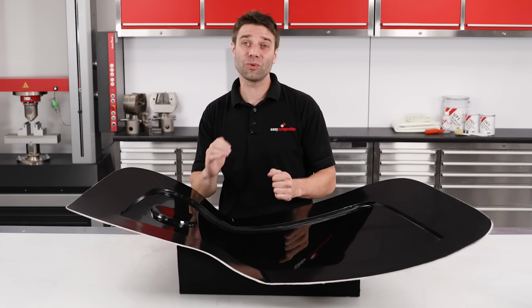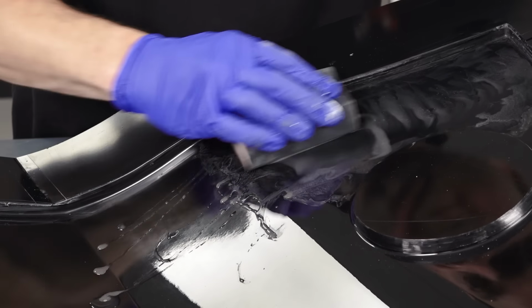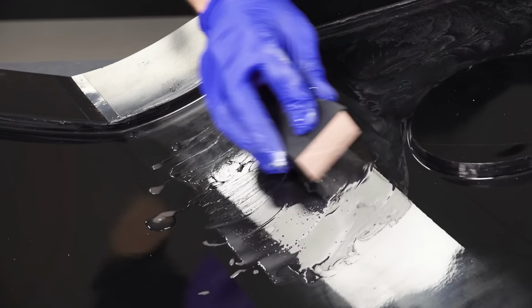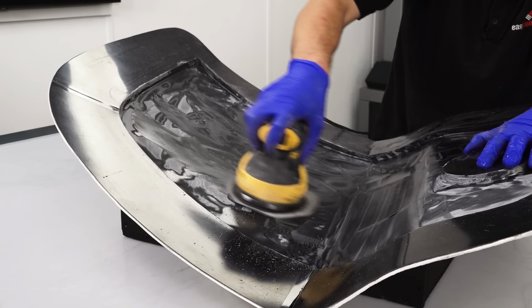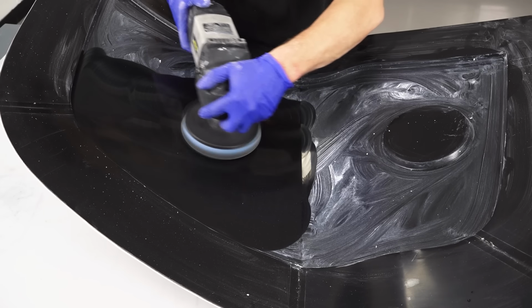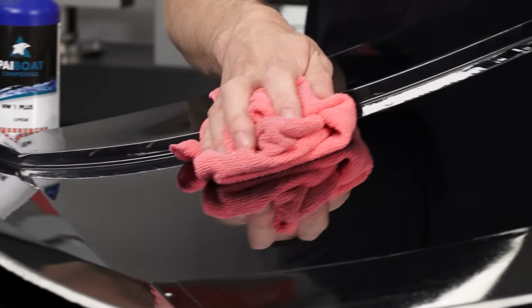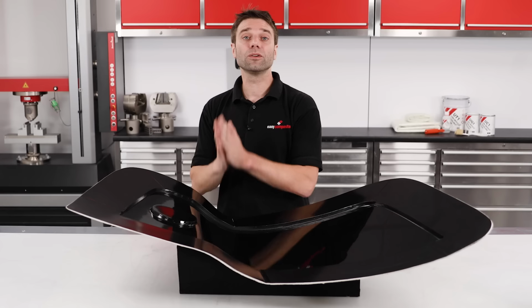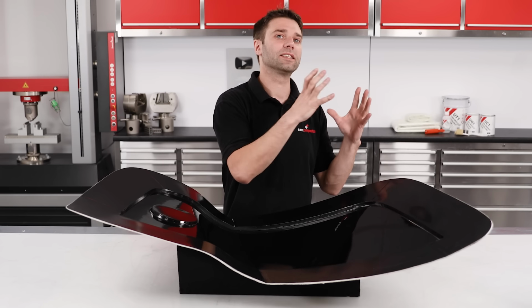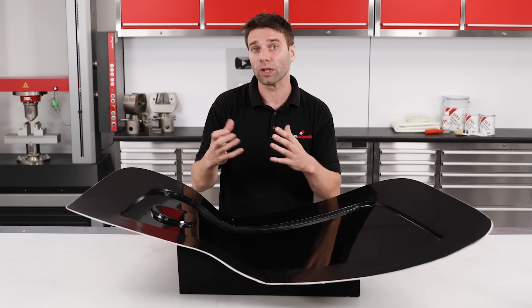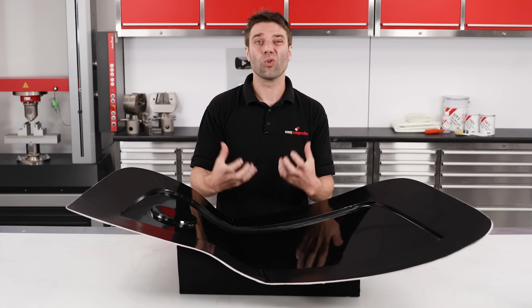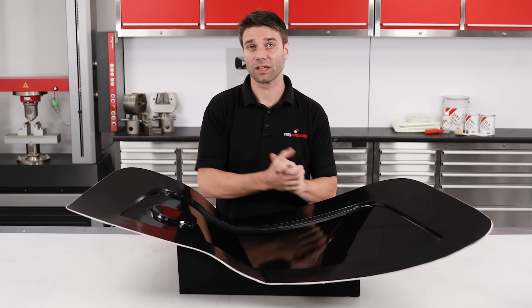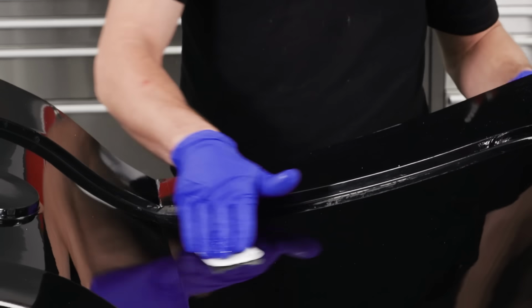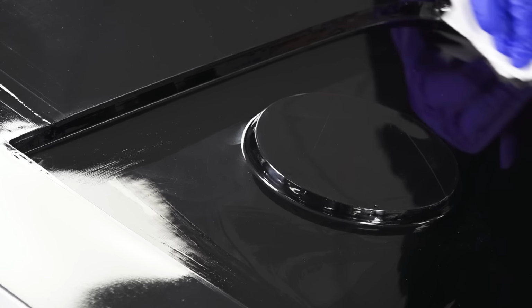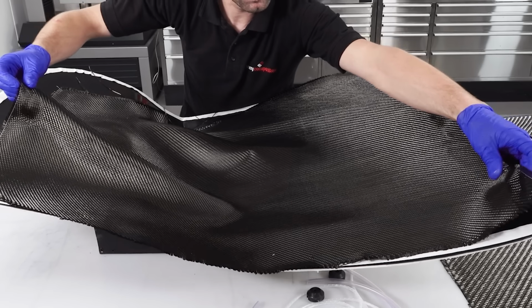Now, this mould could definitely be left like this and it's still going to go and produce excellent parts. But if you did want to take the finish one step further, then the mould surface can be flatted down using 1200, followed by 1500 or even 2000 grit, and then polished up with compound to provide a perfectly flat mirror-like surface. If you are planning to do this, it should be done after you've completed the post-cure. That's if you're doing a post-cure at all, as this will ensure that the mould surface is already fully stabilised before doing the flatting. The very last step is going to be to apply 6 applications of CR1 chemical release agent, and then the mould is ready to start producing its first parts.